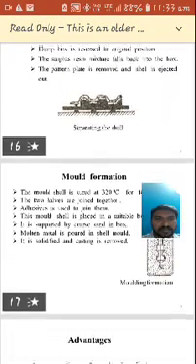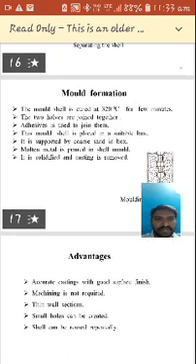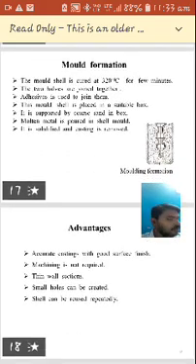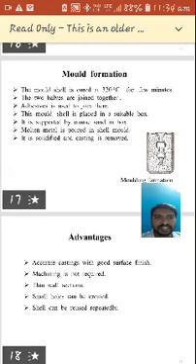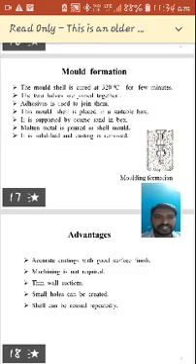See how, after forming the shell, we can form the mold. The mold shell is cured at 320 degrees centigrade for a few minutes.